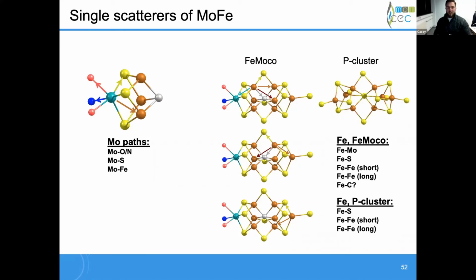From the iron side, it's a lot more complicated though, because again, we have 15 unique irons here. And so in FeMoco, there's iron-molybdenum and iron-sulfur, at least one short iron-iron distance, a long iron-iron distance, and possibly the iron-carbon, although we found you really can't reasonably fit it because it's so light. In the P cluster, it's a little bit simpler, but you still have iron-sulfur and 2 different iron-iron distances that you have to deal with.